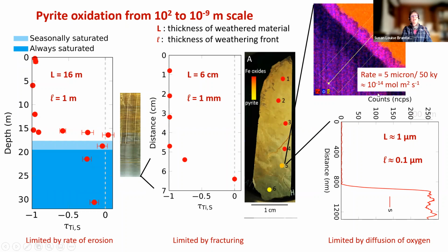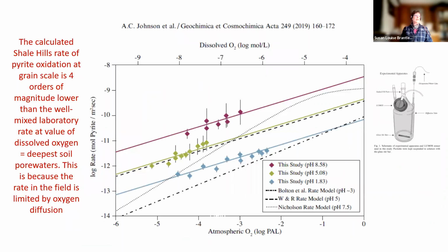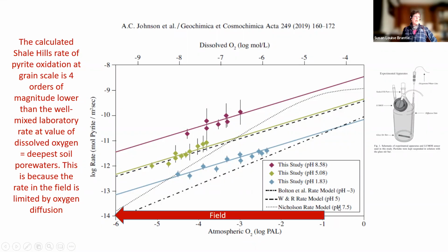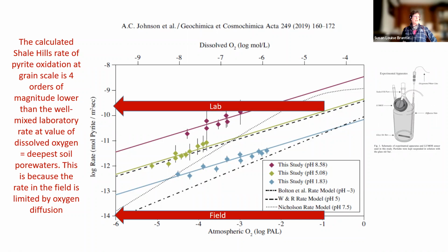You get a rate that's about 10 to the minus 14 moles per meter squared per second. And we can compare this to laboratory rates. This is a complicated plot. This is log rate versus atmospheric oxygen done at different pH values. If you look at our field rate, which was down here at 10 to the minus 14, and we assume that we have oxygen that's something like 10 to the minus 1, like 10% of atmospheric, the lab rate should be here, where we're 4 orders of magnitude slower. And that's actually very consistent with that diffusivity that I mentioned to you.